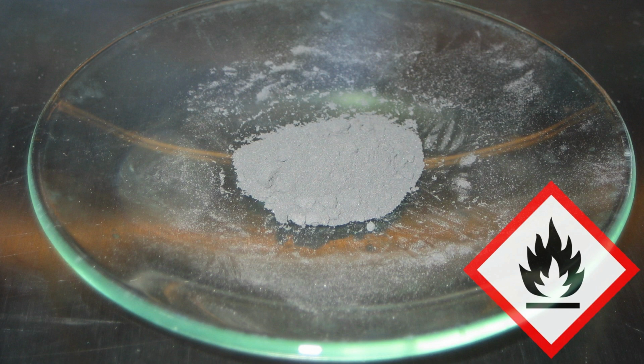The temperature used to leach the alloy has a marked effect on the surface properties of the catalyst. Commonly used temperatures range from 70 to 100 degrees Celsius. The surface area of Raney nickel and skeletal catalysts in general tends to decrease with increasing leaching temperature. This is due to structural rearrangements within the alloy that may be considered analogous to sintering, where alloy ligaments would start adhering to each other at higher temperatures, leading to the loss of porous structure.